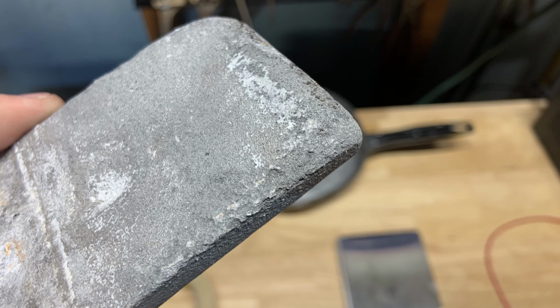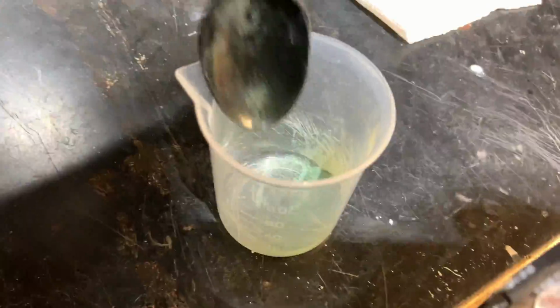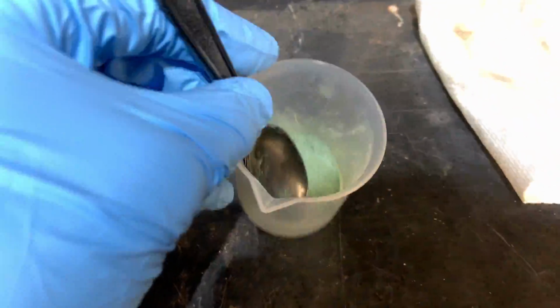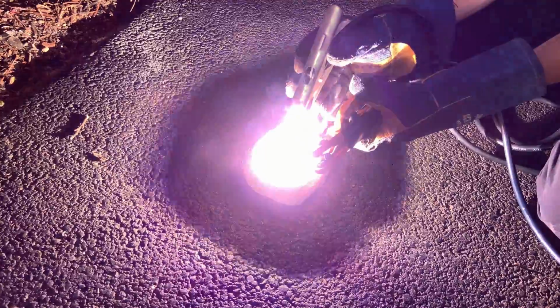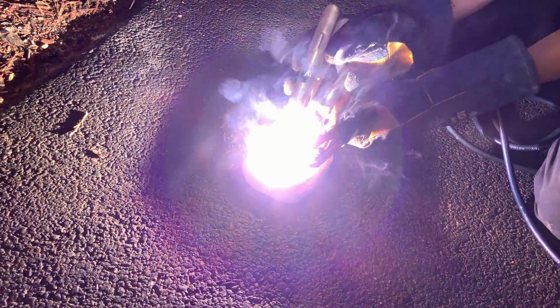And after checking the anode, you can visually see the surface degradation, such as the pitting going on. And in order to be sure that I actually had majority aluminum oxide, I wanted to test by making some rubies, but this didn't go very well because my brick that I was melting it in actually just melted with it. So once I get some more graphite, I can test it again.